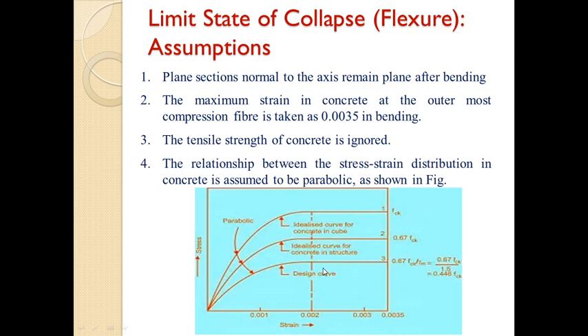The maximum compressive stress in bending is limited to the constant value of 0.446 fck, for strain ranging from 0.002 to 0.0035. The stress-strain relationship is parabolic up to a strain of 0.002, and then the stress remains constant up to the limiting strain of 0.0035.